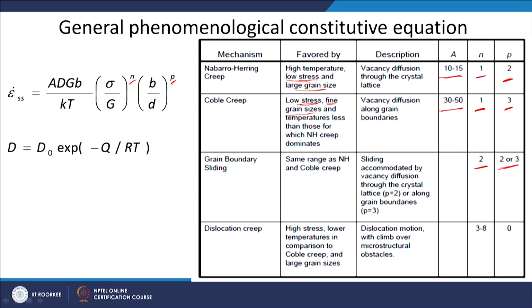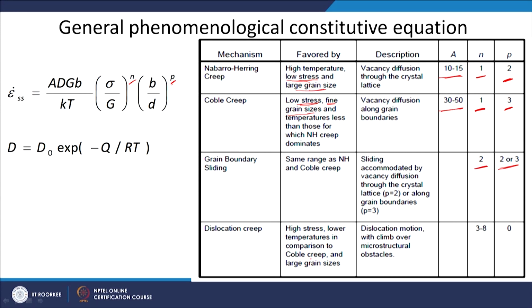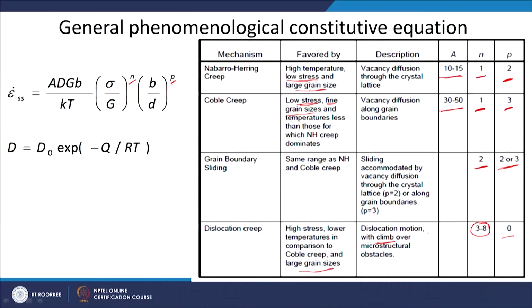Dislocation creep takes place at higher stresses, where dislocations can start gliding under the applied stress, at lower temperature in comparison to Coble creep, and of course at larger grain size. It involves dislocation motion with climb over microstructural obstacles. So climb can take place through high temperature or thermal activation. n is in the range 3 to 8, a very large range. So within each of these ranges there will also be subtle changes in the deformation processes.